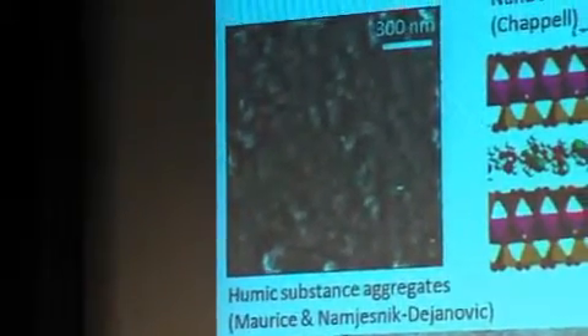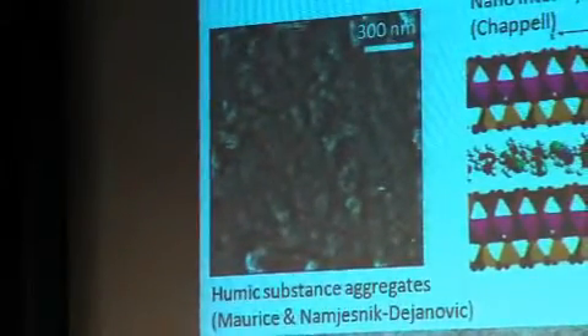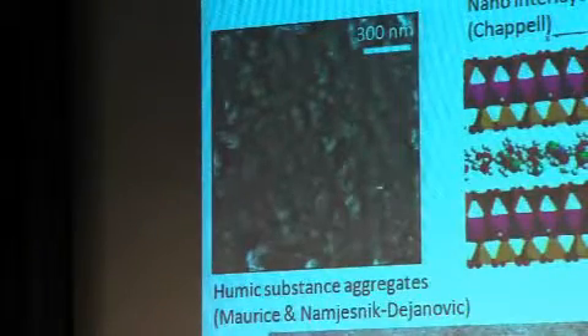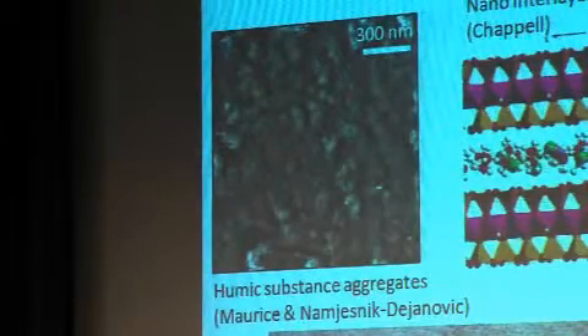And we believe that this ring structure is important because the little domains in the middle have little micro rings inside of it. It's like fractal. Those tiny little rings inside of it may be playing a role in the partitioning of hydrophobic molecules, for example, into the really small little ones that you really can't see too well, and then you've got these larger ones as well. You can kind of see, I'm sorry, this image just doesn't show it very well, little tiny rings within rings. So humic substances, which are out there everywhere, are themselves nanoparticles, and they self-assemble in different ways depending upon what surface they adsorb to.